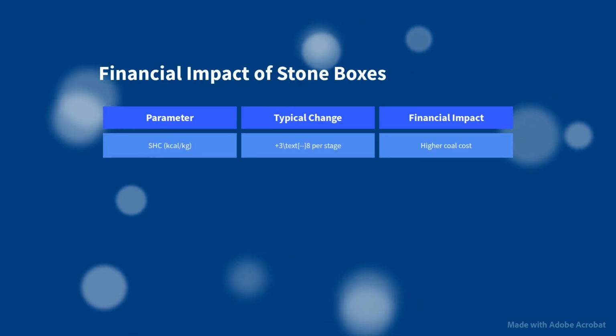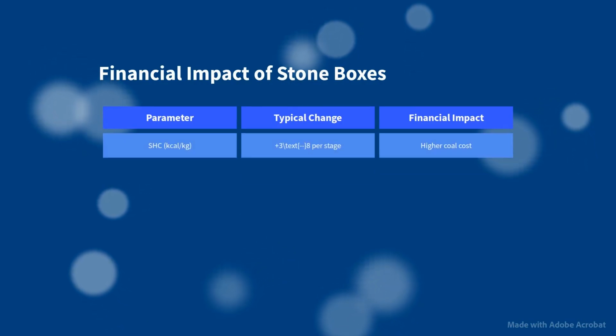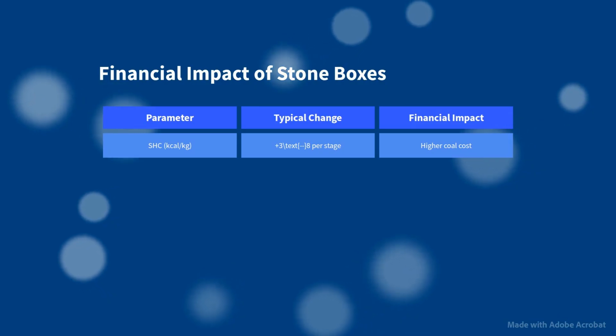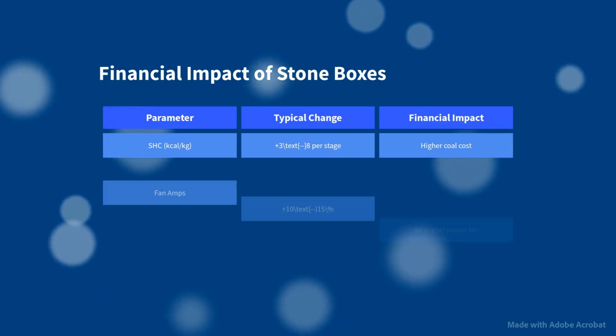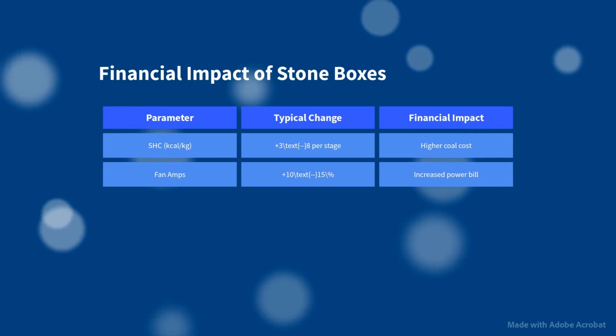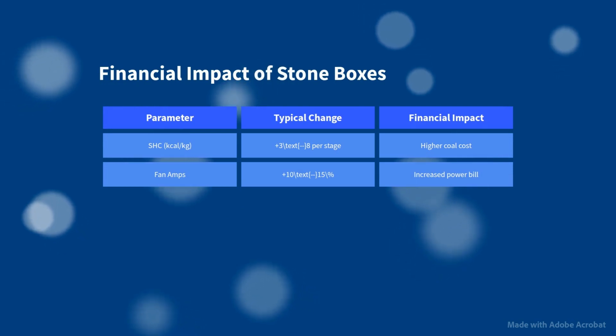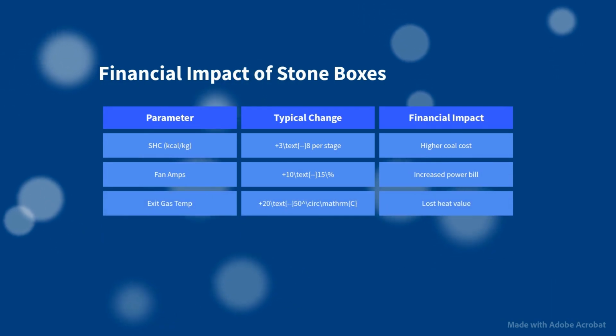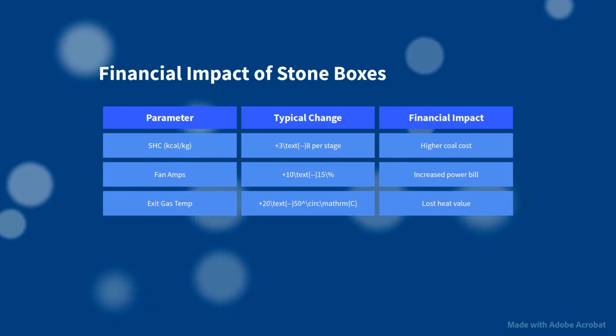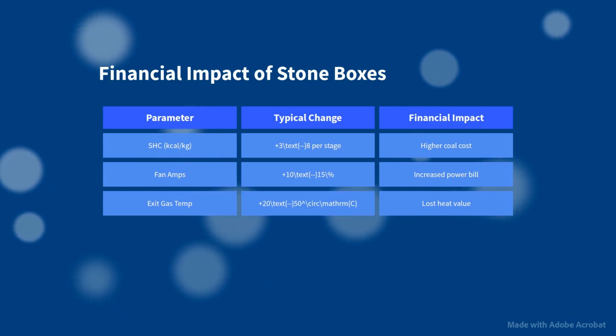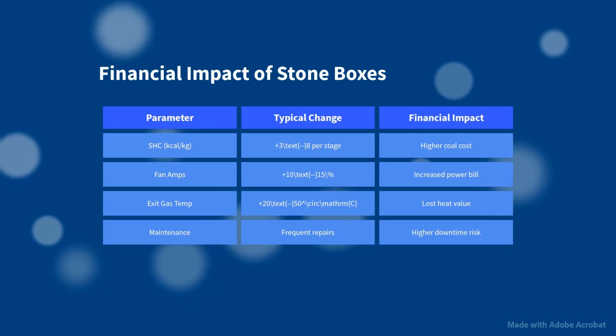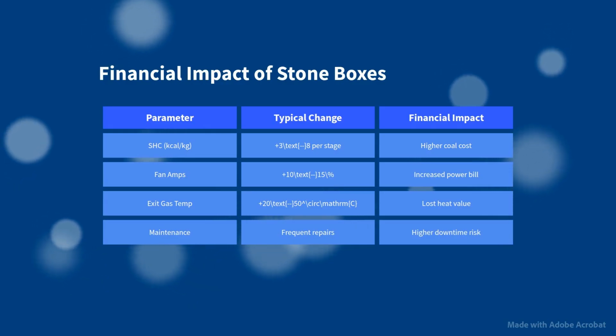An increase of 3 to 8 kilocalories per kilogram SHC per deteriorated stage leads to higher coal costs. A 10 to 15% rise in fan amps means a larger electricity bill for the plant. A 20 to 50 degrees Celsius increase in exit gas temperature results in lost heat value. Frequent maintenance and repairs raise the risk of unplanned downtime and additional costs.